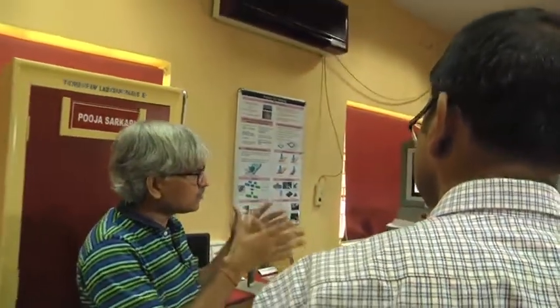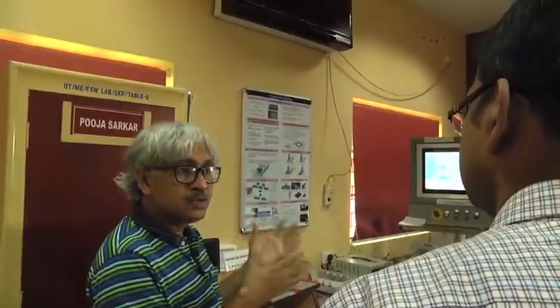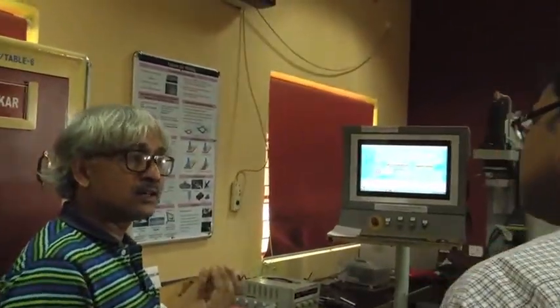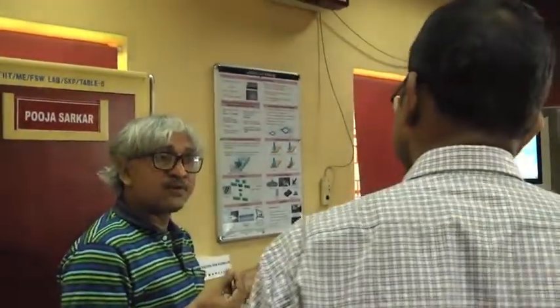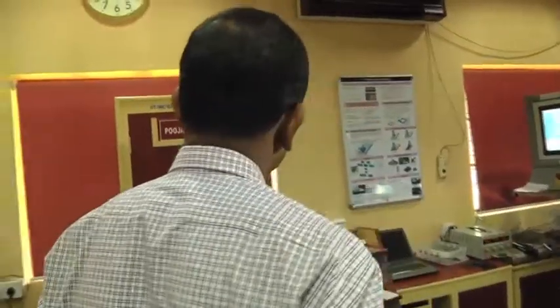In this particular machine, we have engaged two types of sensors. One is the load sensor, which senses force information — if any defect comes up, it will be reflected in the signature of that force. This force sensor data is sent to the cloud. We have also acquired a power sensor. Power has a direct indication about defects — not only the type of defects but also the severity. Depending on the different varieties of defects, the signature gets changed.